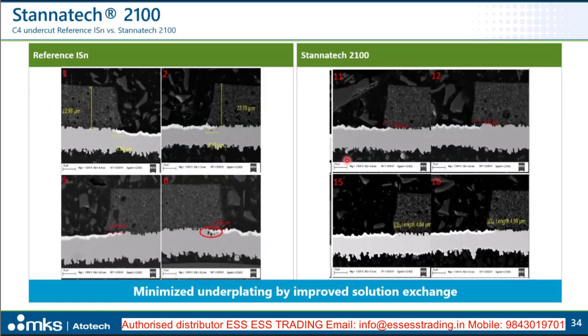And finally, this is also something which we can observe on IC substrate panels. Here is a comparison on the plate on the C4 side of a BGA of the IC substrate. What we see with the reference process is that we have undercuts under the solder mask of up to 10 micron actually in some areas. Here it's also pretty strong, and we even see some copper corrosion in these gaps where we have a poor solution exchange, and this can also be significantly improved.